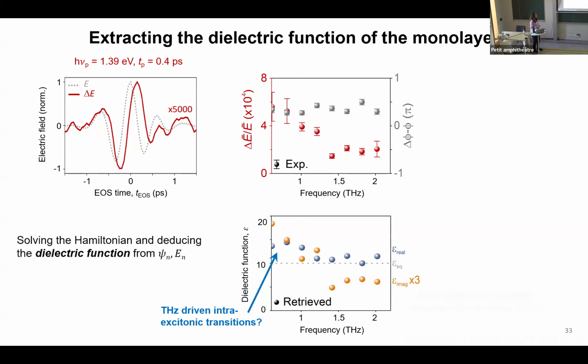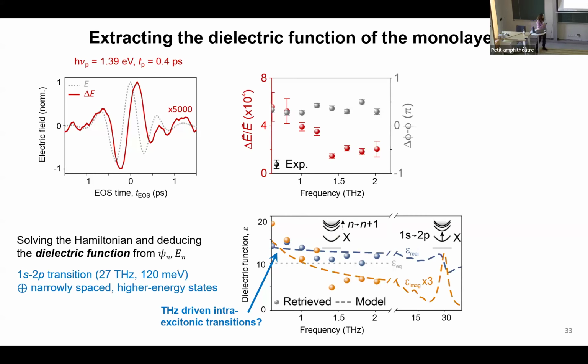To confirm it, we even solved the Hamiltonian of the monolayer and extracted the eigenenergies and eigenwave functions of the material and extracted the dipole moment transition probabilities, and we could reproduce the extracted dielectric function as I show here by these dashed lines. The information that is essential to keep in mind is that indeed what causes this low frequency side of the spectrum is a transition between higher lying excitonic states that have been generated by our pump and initiated by our terahertz radiation.